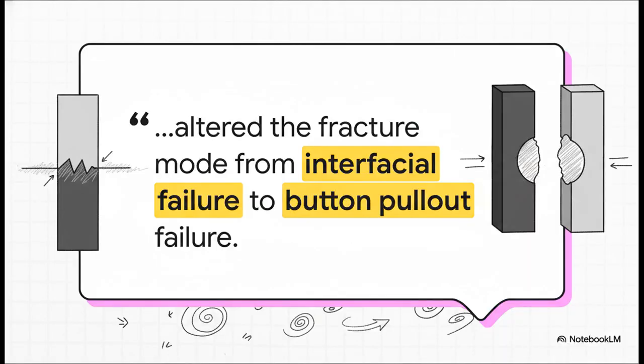Well, interfacial failure is when the weld itself breaks, that chalky layer just cracks apart. But button pull-out failure, that means the weld was so strong that when they tried to break it, the weld held firm, and a chunk of the original aluminum metal got ripped out instead. The weld didn't break, the metal itself did. That is the ultimate sign of a successful weld.